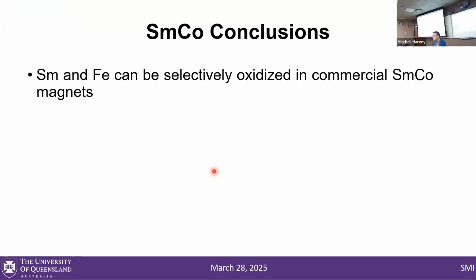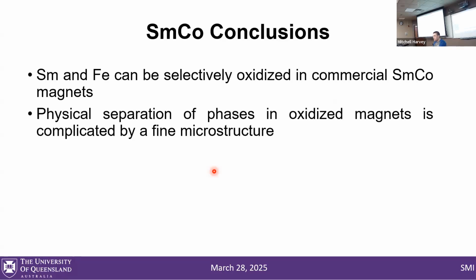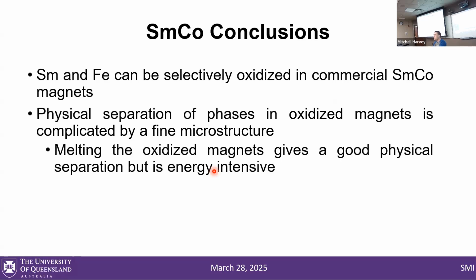So this is all of our work to date. We've demonstrated that both samarium and iron can be selectively oxidized in commercial samarium cobalt magnets. Physical separation of the phases is complicated by the really fine microstructure, but the melt coalescence seems to be a valid method if nothing else works.